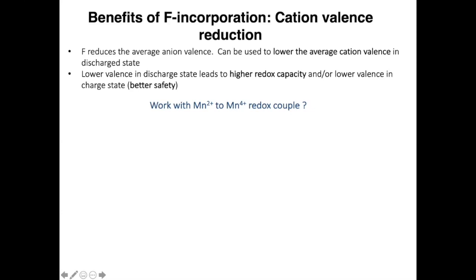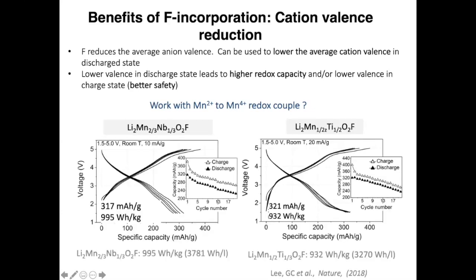as manganese 3. So we were able to synthesize materials as manganese 2 by putting in a lot of fluorine. This is 33% fluorine, and we add a high valent ion to further lower the valence of the transition metal. And so these are manganese 2+ compounds, either with niobium or with titanium as a high valent charge compensator. And so these now start as manganese 2. You can charge up to get very high capacity. So we're over 300 milliamperes per gram here. Again, over 3000 watt hours per liter, even approaching 4000 watt hours per liter.